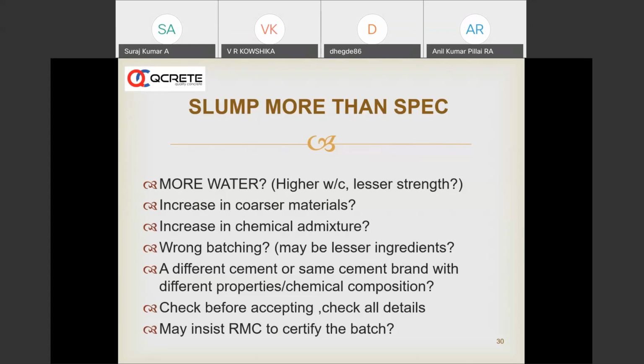Another point which we need to discuss is that, let us say the mix design is done for 3 hours slump retention. Somebody wants the concrete to have a 150 slump after 3 hours. For whatever reason, he has told the ready mix company to give a mix which is going to give 150 slump after 3 hours. The truck reaches the site in 1 hour. So definitely the slump will be out of spec, and the slump will be very high if the truck reaches at a much earlier time than anticipated.